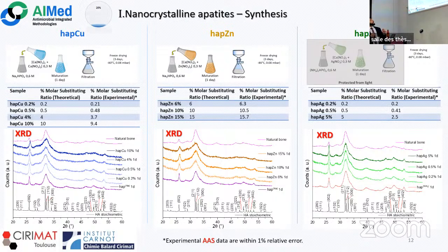We observe that, as I said before, we work on the substitution with copper, zinc, and silver. And the first thing that comes up is that at all the tested substitutions, for all the samples, we don't observe in the XRD patterns any secondary structure. So we have attained our first objective, that is to have monophasic materials.